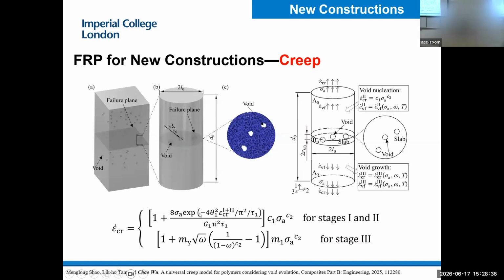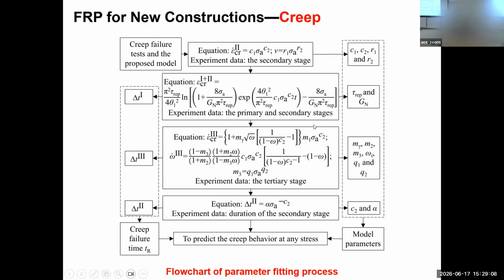Based on the molecular behavior of polymer material, we developed a theoretical model that can describe the full three stages of polymer material under creep. This is expressed as a strain rate. We have a lot of material constants to be fitted using experimental results, but it's much more reliable and much easier than the available models in the literature. This is the process for fitting the material constants in our model.